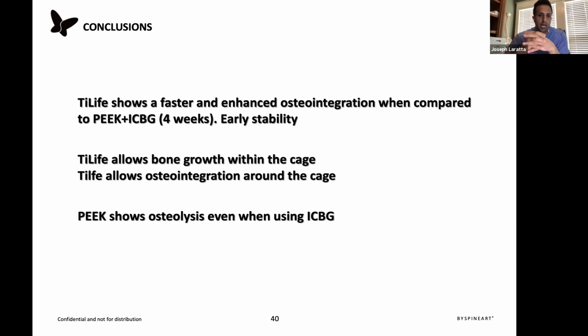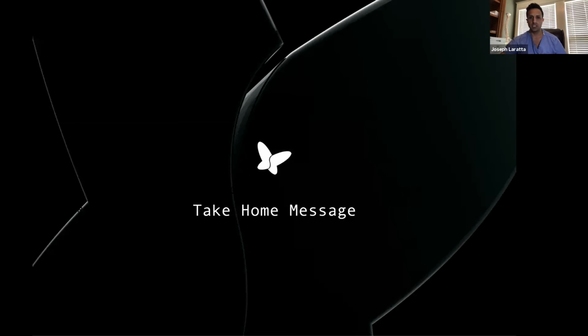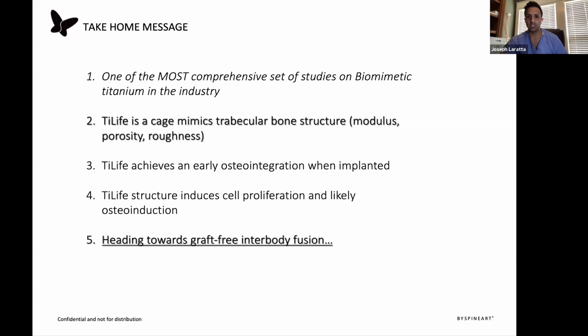In conclusion, I think that TiLife shows a much faster and enhanced osteointegration when compared to PEEK plus autologous iliac crest bone graft, even at 4 weeks. This leads to early stability, and this is where we started from. What leads to fusion? Stability, size of implant, delivery of graft. TiLife allows bone graft through the cage, around the cage, while PEEK shows osteolysis even when using autologous iliac bone graft. So kind of what's the take-home message for all this?